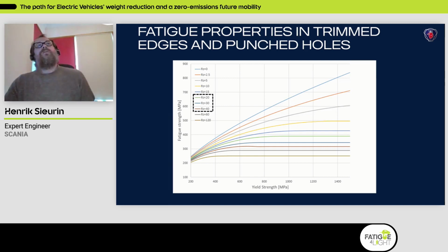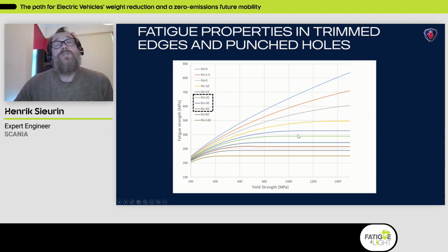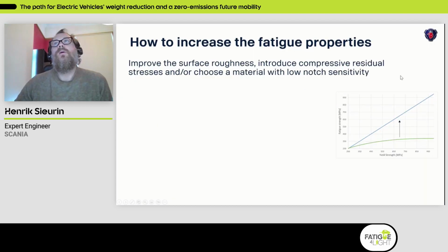But in a component, like a sheet component, the surface roughness for a punched hole might be somewhere between 20 and 30 Rz value, and for a trimmed edge, it might even be between 30 and 40. And then you have this brown or blue line here. As you see, increasing the yield strength increases the fatigue strength up to about 600 in yield. But then it makes no sense increasing material strength anymore. So this is how we have thought in the past, maybe.